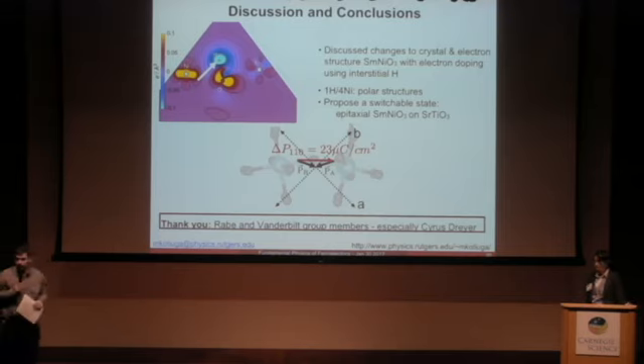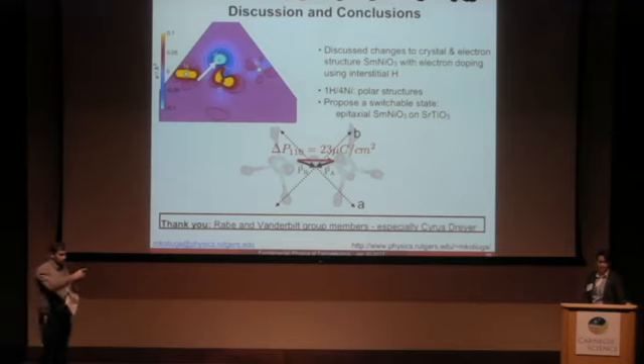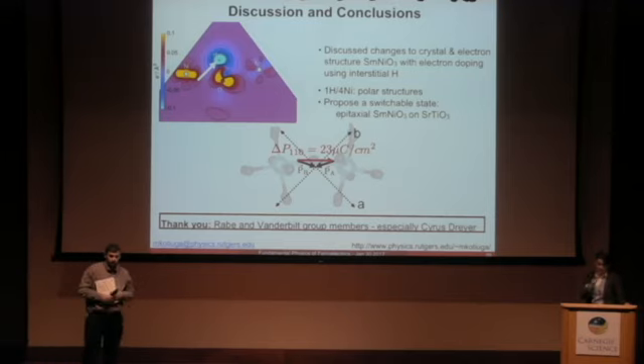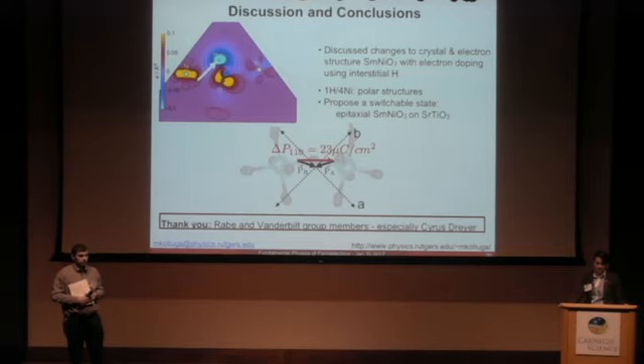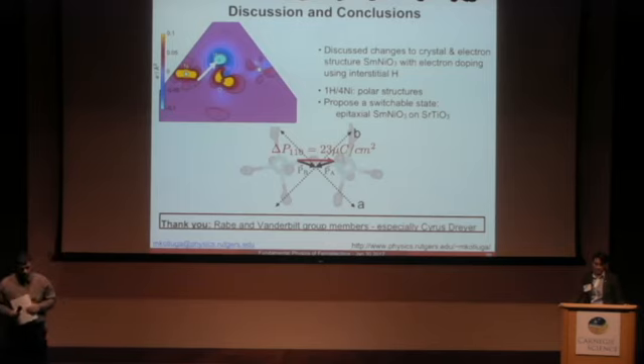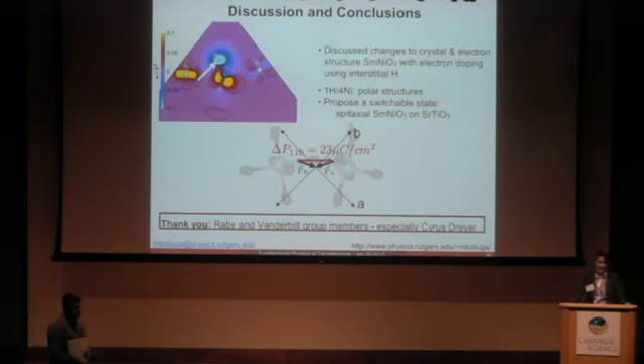Okay, questions? So in your calculation, it looked like you used a G-type magnetic order. Yep. The nickelates exhibit an E-prime type. Right. Do you know the sensitivity of the polar structure or the charge order that you see on the magnetic order? Yeah, so first off, to get the E-type, you need a very large unit cell.